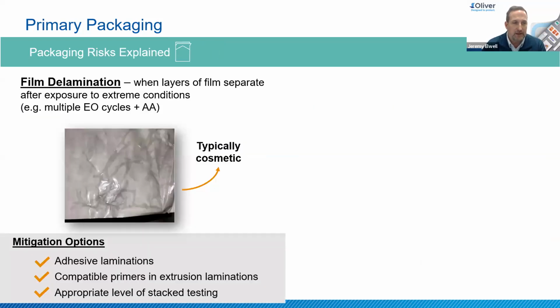So starting with film delamination, this is a phenomenon when layers of film separate after exposure to extreme conditions. We have written here EO cycles, but also any type of gas sterilization, combined typically with accelerated aging and maybe other stack testing afterwards. And typically it's cosmetic. If you do testing on the sterile barrier, you're not always going to see a breach of sterile barrier, really just an eyesore. The film's separated from itself, and it looks like it's probably weaker, but it could pass further testing. So we do call it cosmetic to begin with until that further testing is performed.